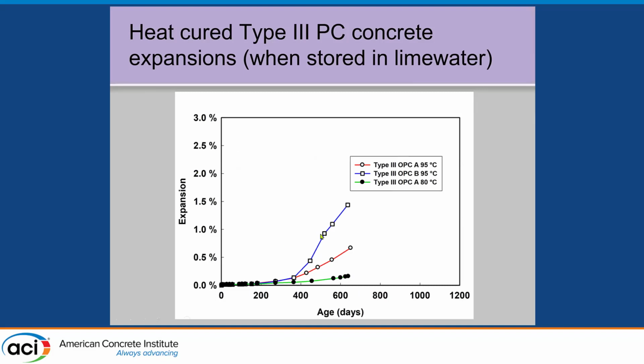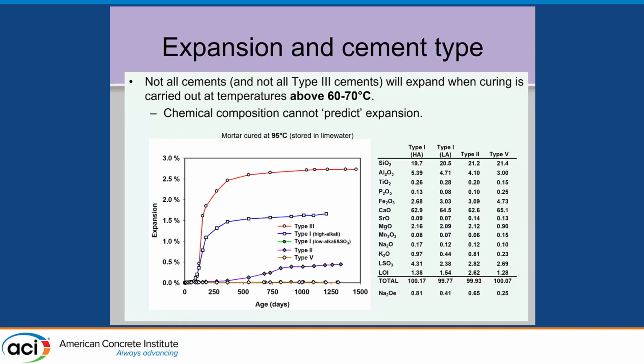So I didn't get a chance to update this graph, but you see the same story. When these concretes were exposed, type 3 cement concretes, two different ones here, at 80 to 95 degrees, we're getting deleterious expansion over time. But it's happening after about a year. But not all cements will expand when you cure them at these high temperatures. And not even all type 3 cements will expand at those temperatures.